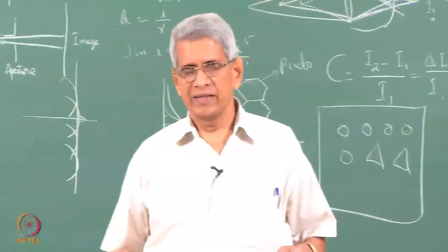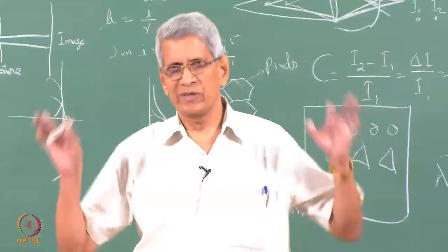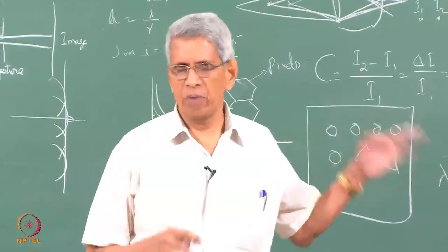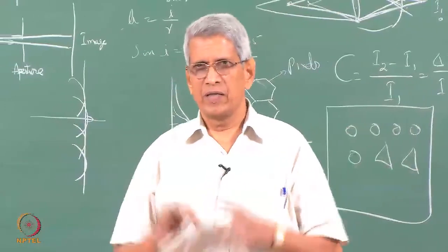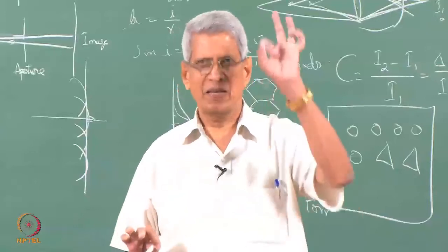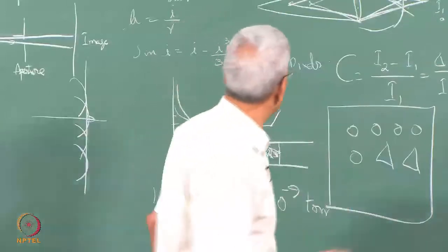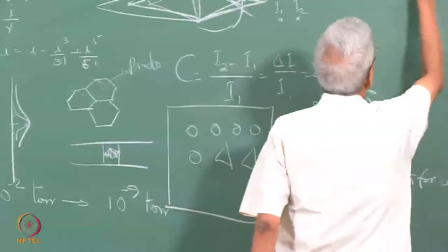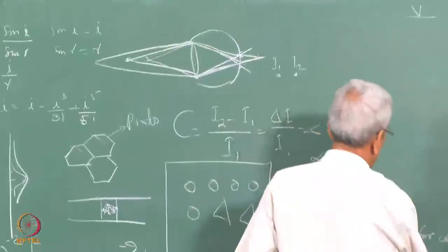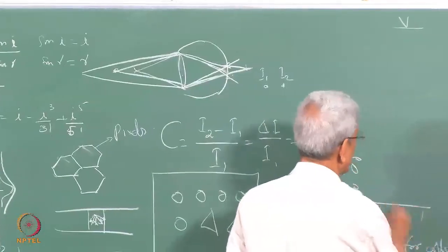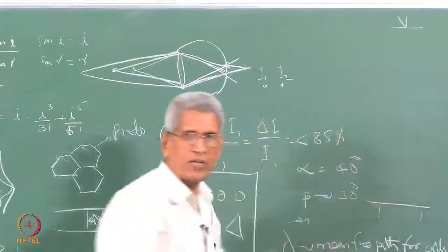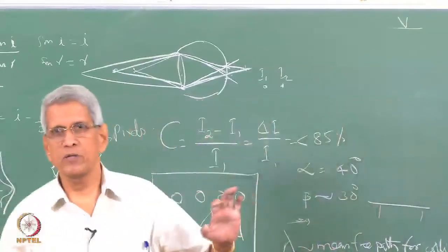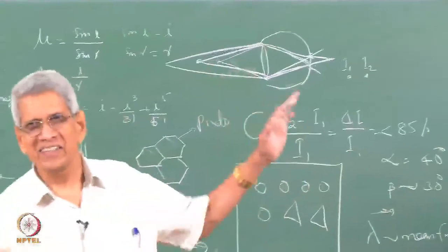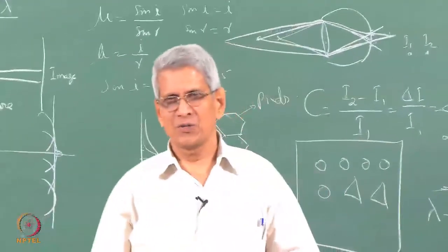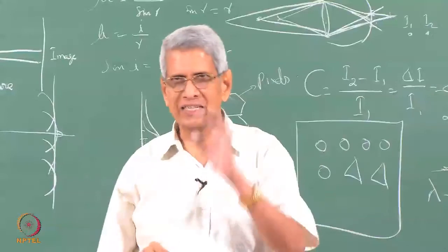As we evacuate, the number of molecules gets reduced, the volume remains the same, and the mean free path increases. The minimum vacuum should be such that when an electron is emitted from the electron gun at the top, from the filament, until it reaches the photographic device, the mean free path should be larger than the distance it has to travel. So that puts the criterion.